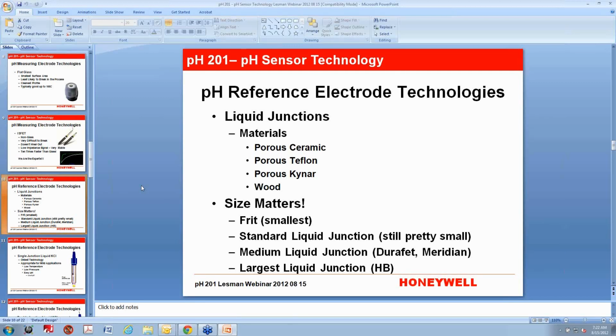and a frit is just terminology for a very, very small hole. And if you look at some laboratory sensors that are completely glass, you'll see the measuring electrode, and then if you look up on the side, you'll see a tiny hole in there. And that hole, that's your liquid junction, and it allows you electrical contact. And that's really a nice liquid junction for a laboratory type sensor, because a lab sensor goes into something nasty for just a few seconds, measures it, comes back out. So it's not likely to get damaged very quickly.